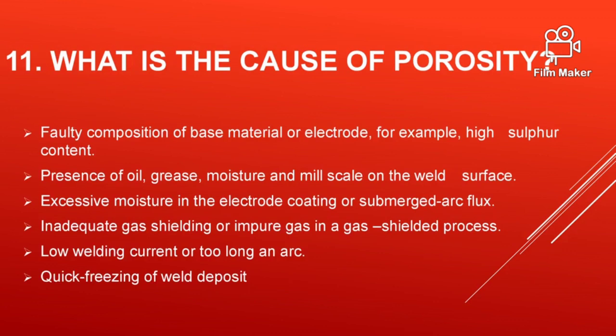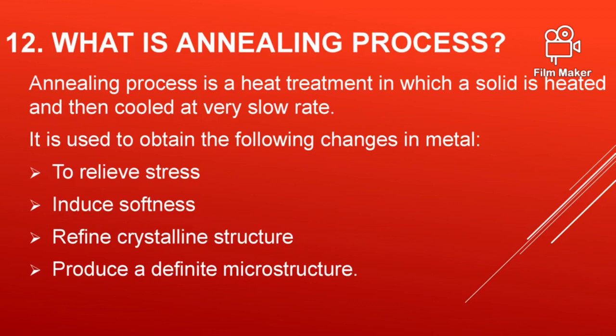What is the cause of porosity? Faulty composition — for example, high sulfur content — presence of oil, grease, moisture, and mill scale on the weld surface, excessive moisture in the electrode coating, inadequate gas shielding, low welding current, and quick freezing of weld metal.